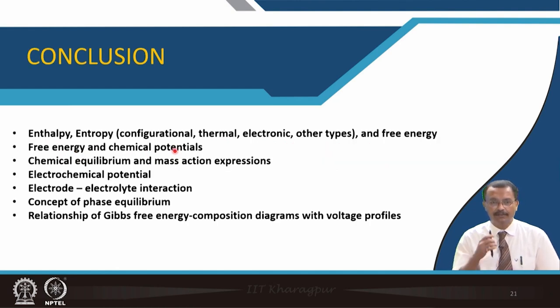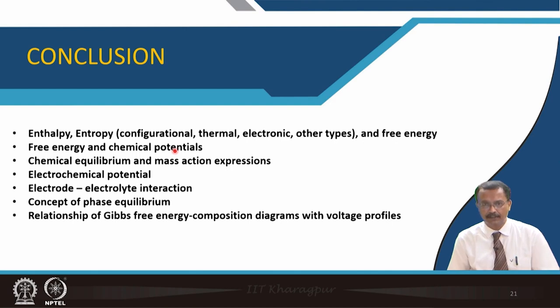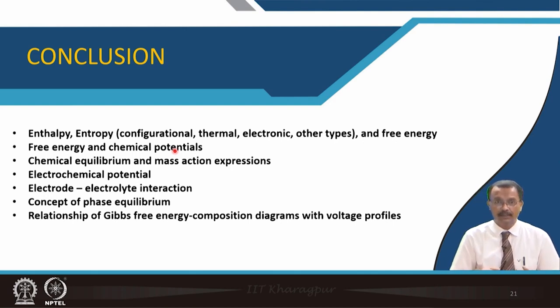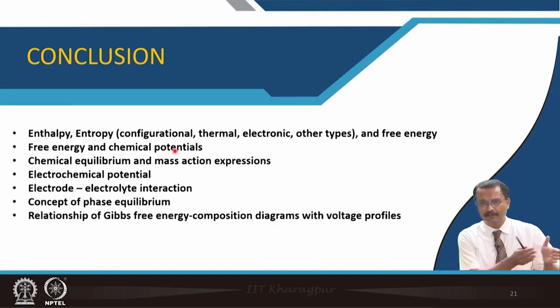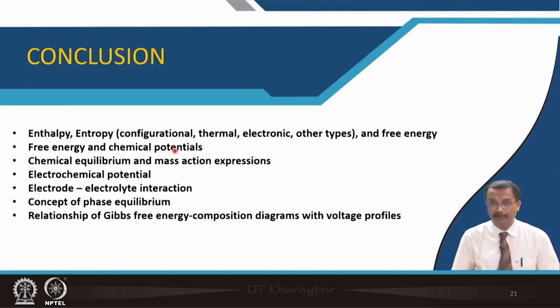So, in this particular lecture we have introduced enthalpy, entropy, configurational, thermal, electronic and other types, then free energy, then free energy and chemical potential, then chemical equilibrium and mass action expressions. Then we introduced the term electrochemical potential, then electrode-electrolyte interaction, the concept of phase equilibrium, at least in the equilibrium state, and how you can estimate the open circuit potential under equilibrium. And then finally, I have touched on the free energy composition diagram with voltage profile.